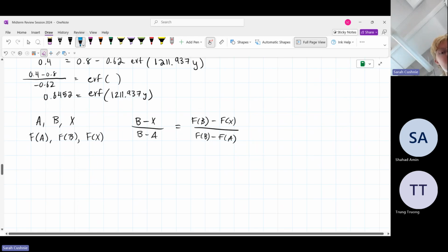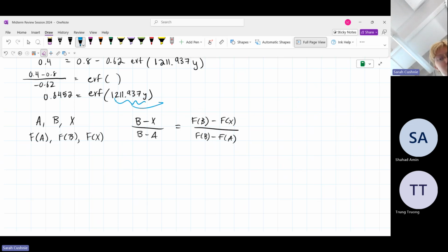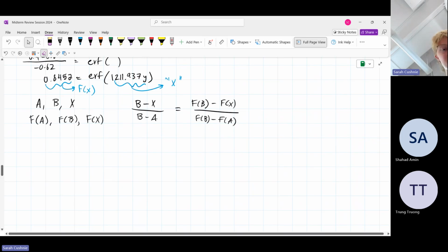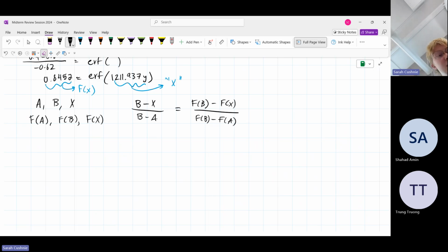So in this case, we're going to call the value within the error function x, and this value here is f at x, because that's what the error function is equal to. And then we can look at the error function in the textbooks to find the matching values that would surround this f at x. I did it differently when I did it back then. No, I can figure it out. So we are going to have 0.70 minus x over 0.70 minus 0.6.